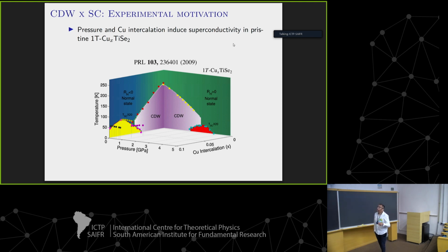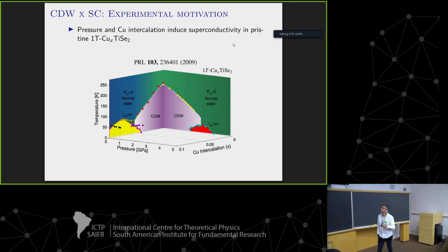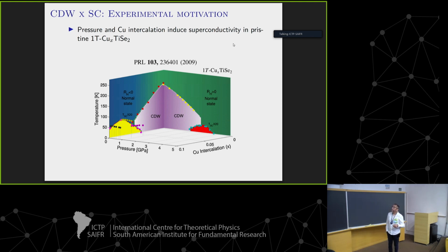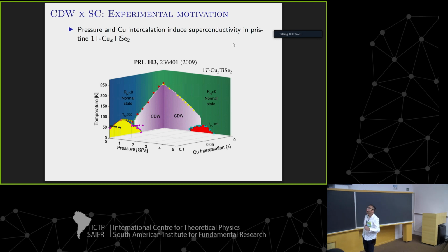So after reading this paper, we get two important insights. First is that the nature of this charge density wave phase here is commensurate, and on the other hand, the superconducting phase here can be explained by the BCS framework.